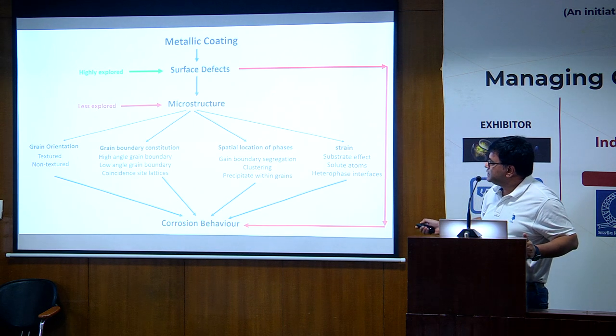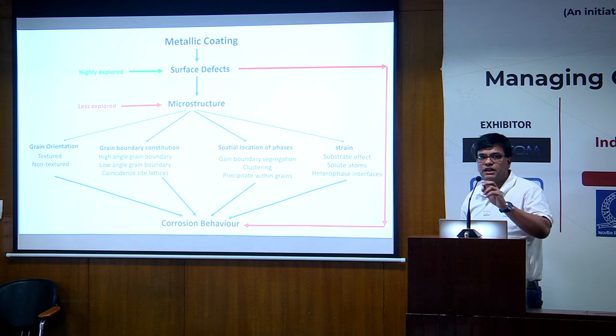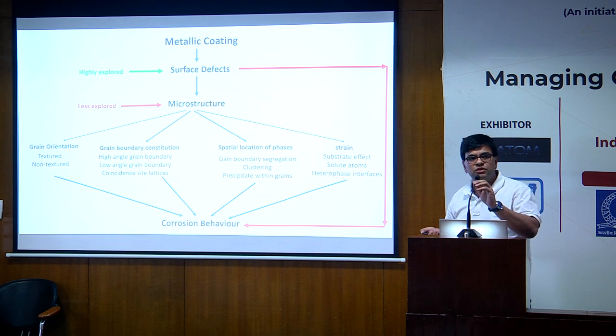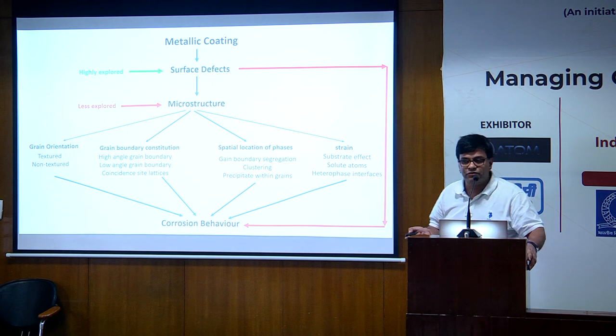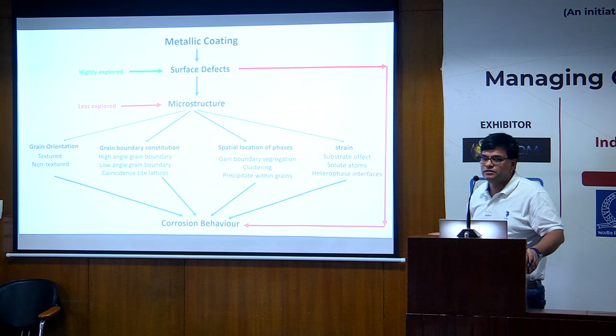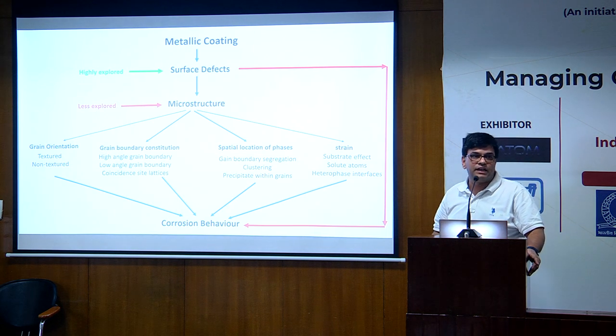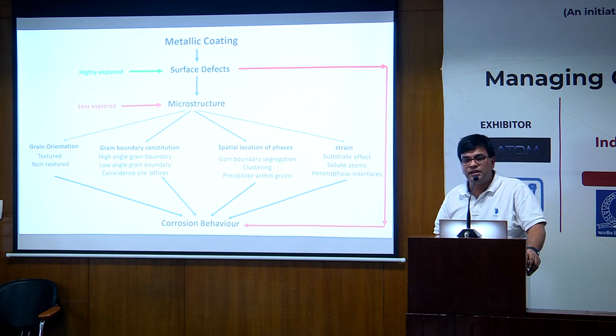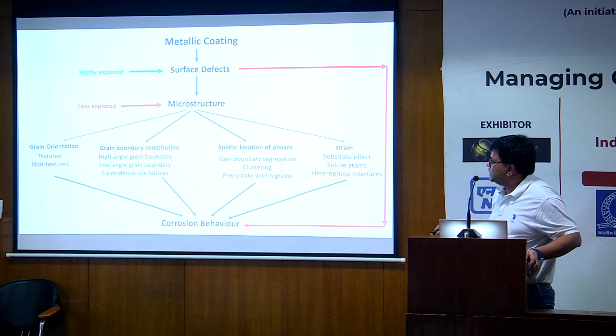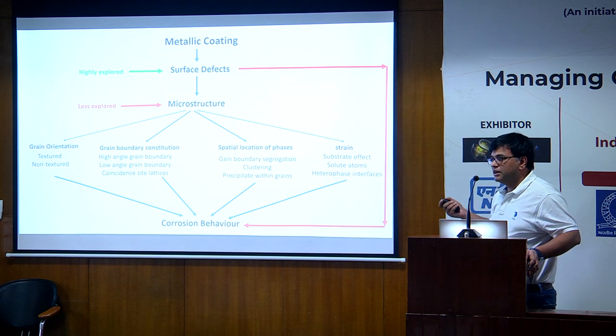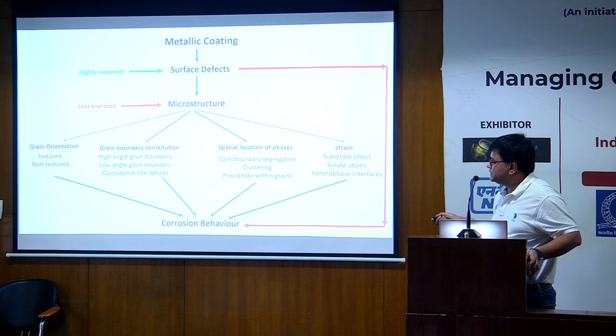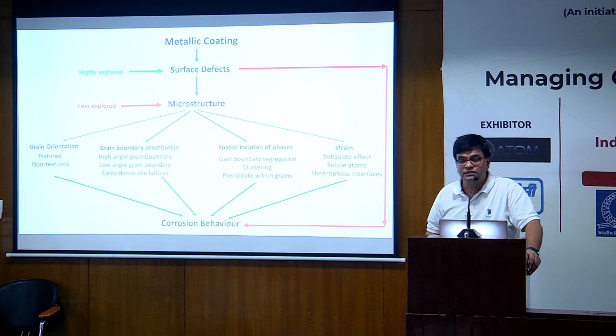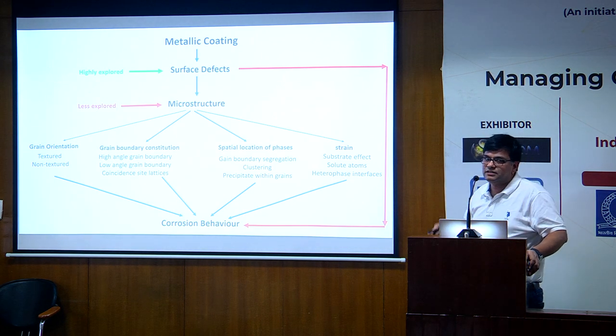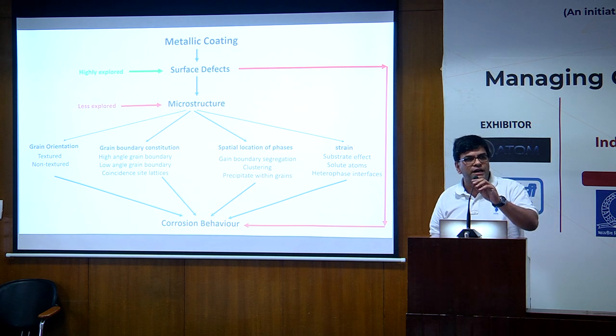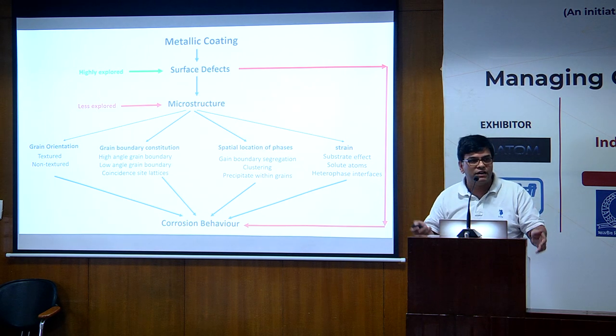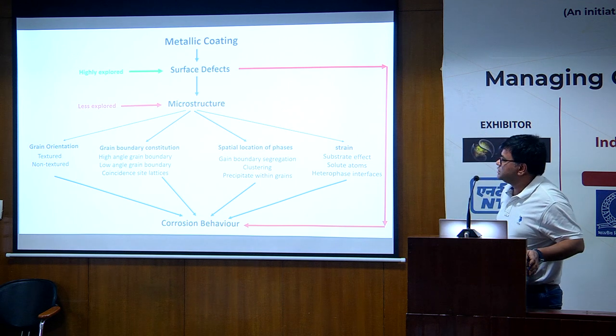The other important thing is that if you're looking at coatings which contain more than one component, you would always have some phases formed, and how those phases are distributed in the microstructure, whether they are at grain boundaries or in the grain interior, is also important, because that will majorly determine your corrosion behavior based on the extent of galvanic coupling happening in the coatings. We also look at the strain. If you have higher strain and lower strain regions, those can galvanically couple and lead to high corrosion behavior.